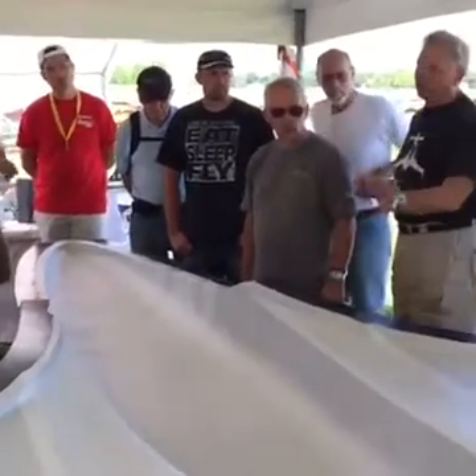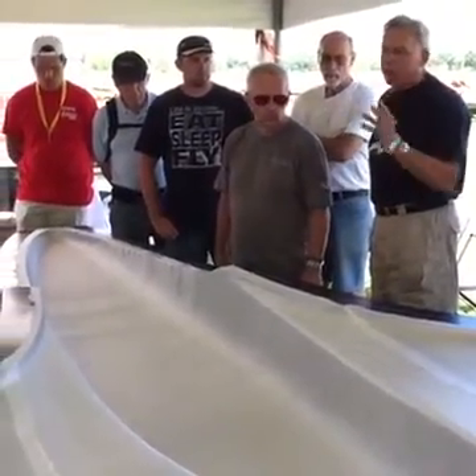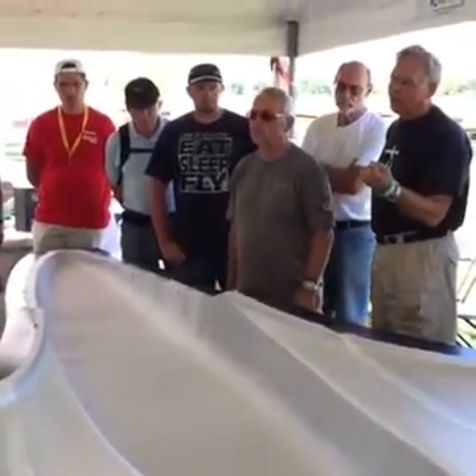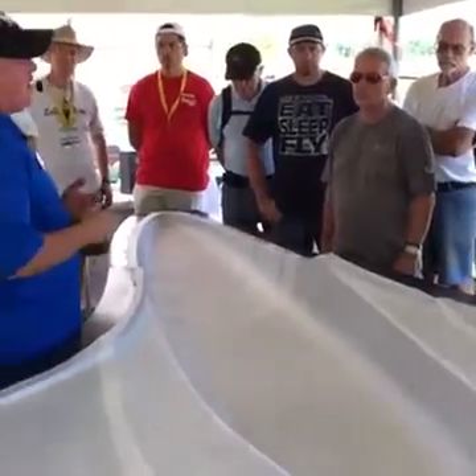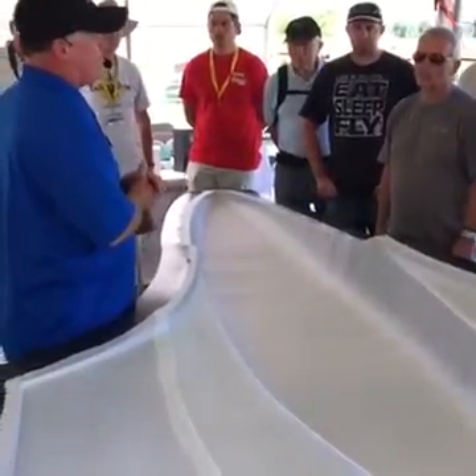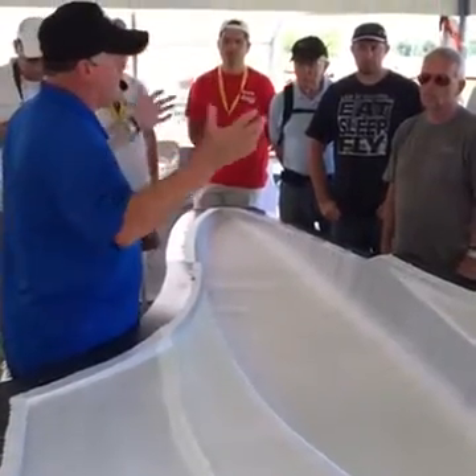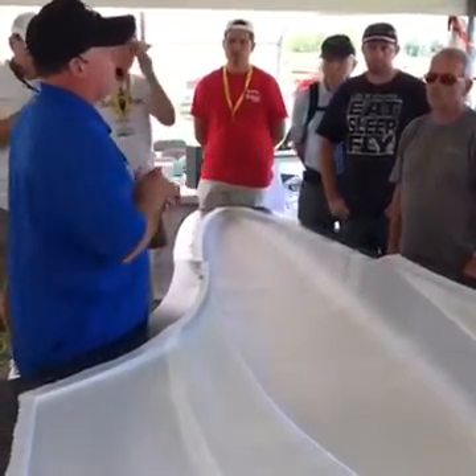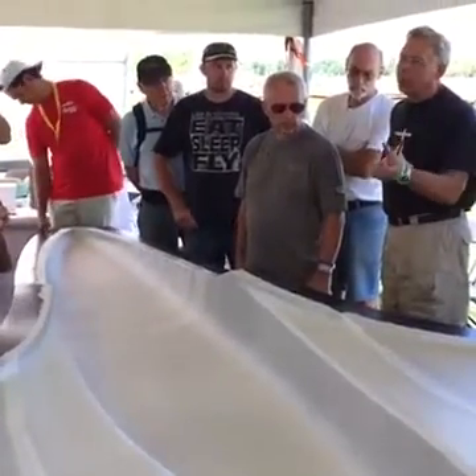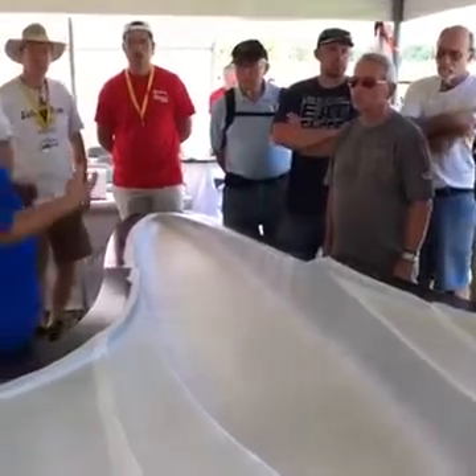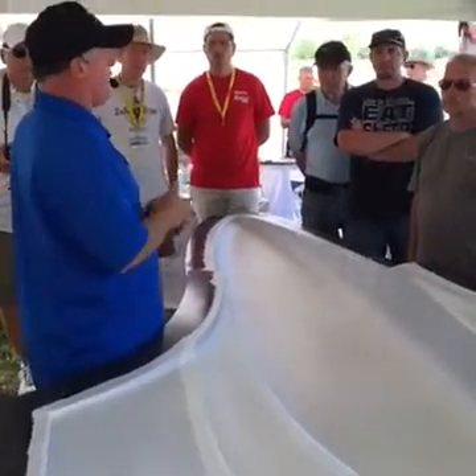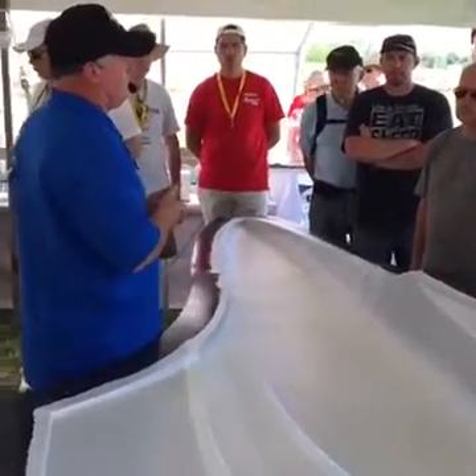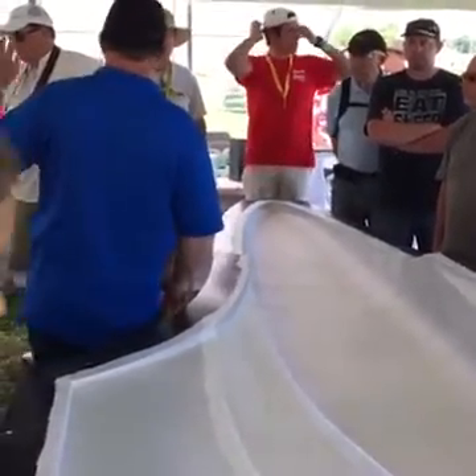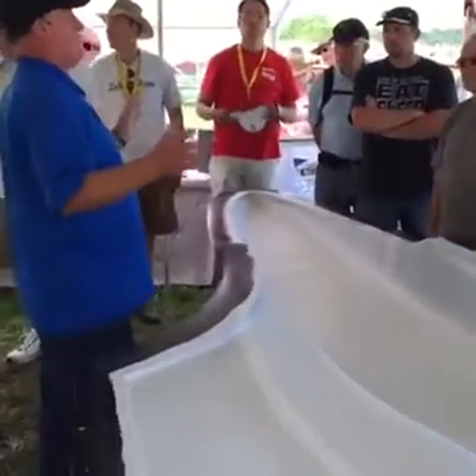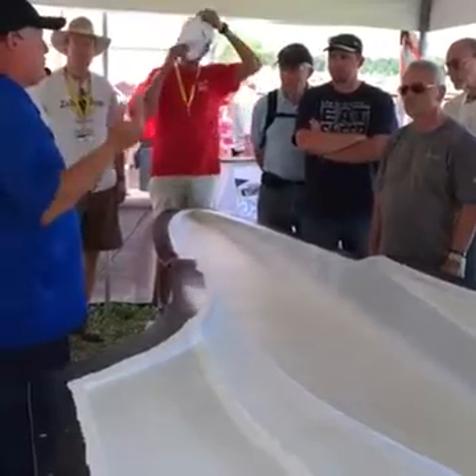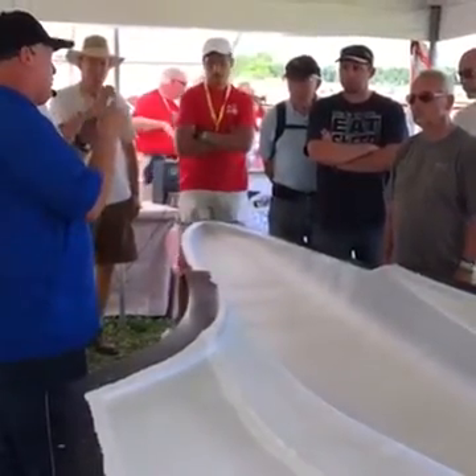Now the spray that you're using to contact the fiberglass in the mold, how much contamination is that against the system? On this one, it'll probably wind up being about 2% of the total viscous material consumed within the part. So does that resin eat into that? The amine and the hardener will eat that, but it won't 100% dissolve it. I'll get about a 98% attack. On the Scott Bader resin systems, we'll get 100% meltdown. So that spray adhesive will actually go completely away and become part of the resin system.